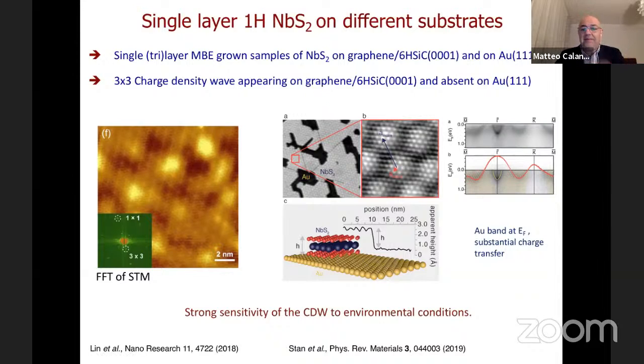So the situation is extremely puzzling. And the absence of charge density wave is seen in ARPES on the gold 111, also with the occurrence of a metallic band. So it's clearly out of question. And the charge density wave, on the contrary, on the 6H silicon carbide is seen very well in different experiments. In one experiment, sorry, not different, one experiment in which STM data are shown, and this is in Nano Research.